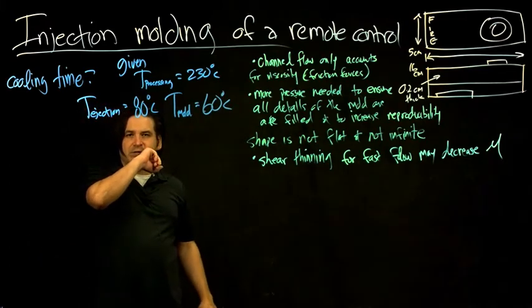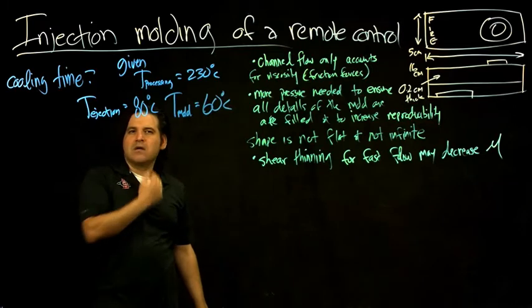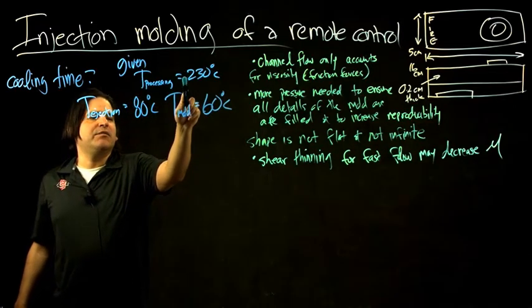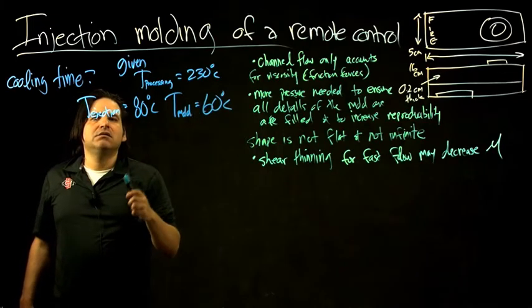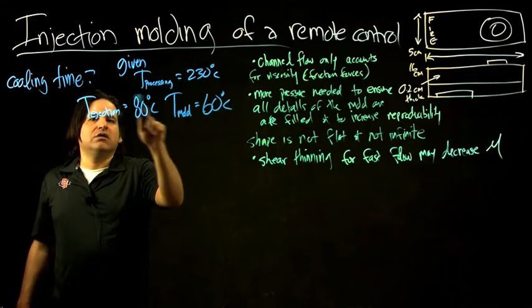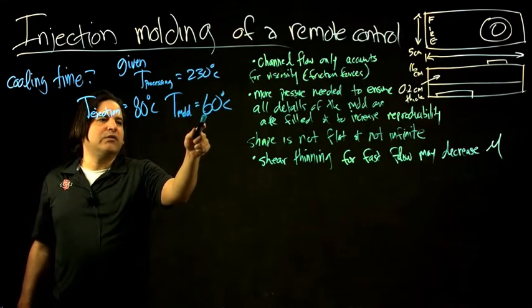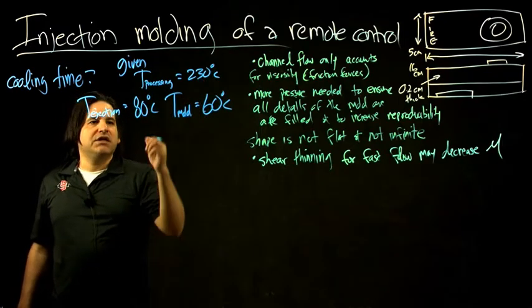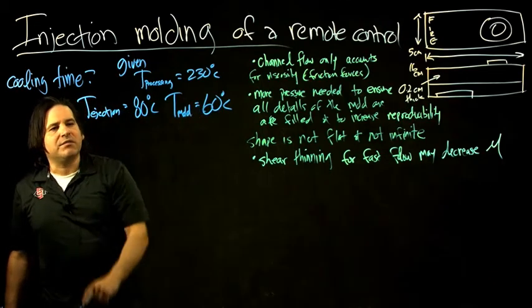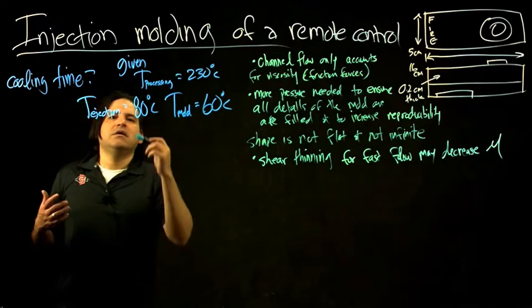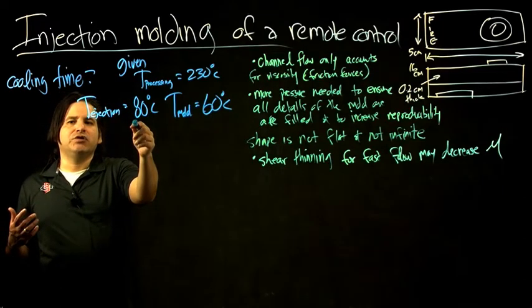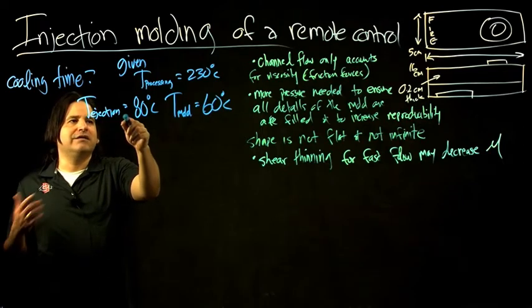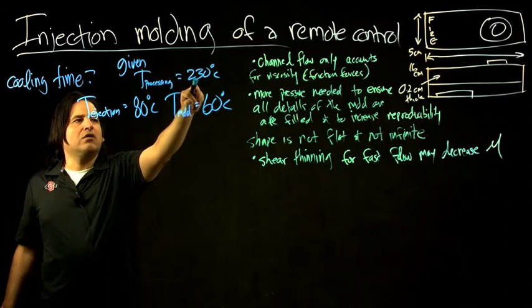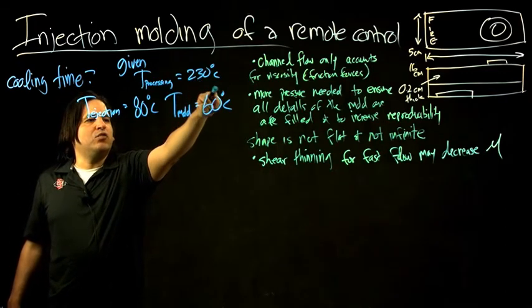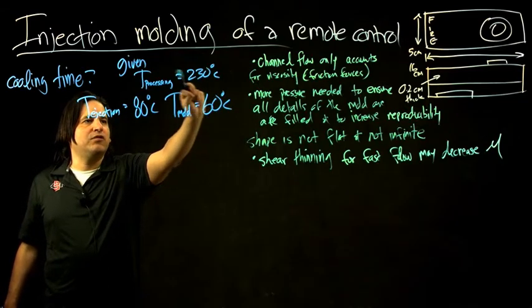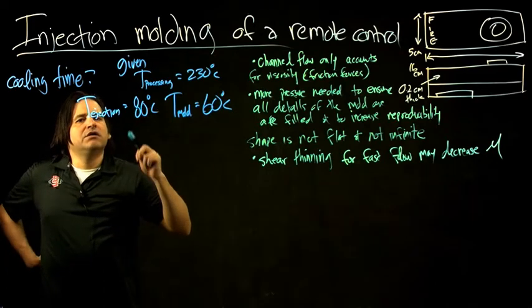So as we can imagine, these determine the time it takes to cool, meaning that if we need to keep it melted, this is the temperature that we keep the mold at. And we don't wait until the part reaches the temperature of the mold, because we can potentially speed up the process if we don't wait until that occurs. So that's a separate temperature called the ejection temperature, which would be the maximum temperature you would wait for, because ideally you don't have to wait for the lower one. It starts off at this temperature, and if you wait until it reaches 60, that'll take a much longer time than if you wait until it gets to an intermediate temperature.